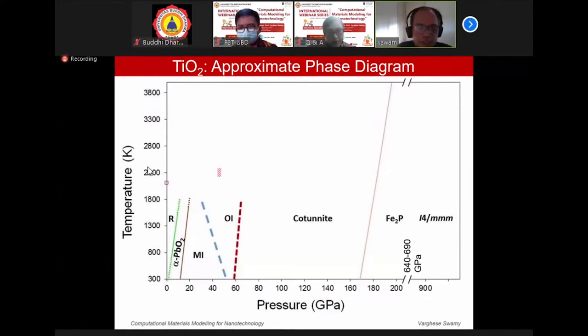And here we can see the temperature-pressure phase diagram of titanium dioxide. So the pressure is along the x-axis and temperature along the y-axis. You can see that the stable phase at ambient conditions, when we say stable, thermodynamically stable, not kinetically stable, is rutile, represented by R, that transforms to an alpha PbO2 structure. The structure of the alpha PbO2 mineral is called columbite.